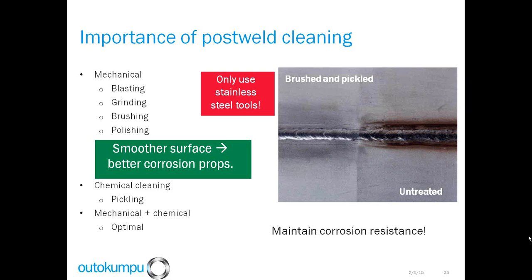The importance of post-weld cleaning. First of all, we want to use stainless steel tools. Basically, with post-weld cleaning, we want to restore the corrosion resistance. We can use mechanical means as shown in this slide at the top. Chemical cleaning such as pickling with acids. And the optimal process is actually removing it mechanically and then finishing it off with a chemical process such as pickling. And this slide shows the difference between brushed and pickled and then the untreated surface with the heat tint.